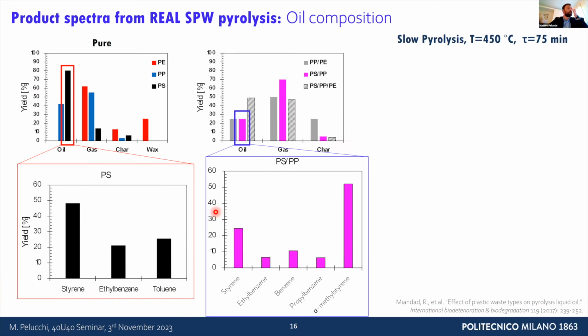If you increase the complexity of this mixture, moving to binary mixtures, let's take polystyrene with polypropylene. The oil fraction has dramatically decreased by 4 times, and the products you're forming are also very different. You still have styrene and ethyl benzene, but now you start to have some alkylated aromatics, for example propyl benzene, alpha methyl styrene, and so on.